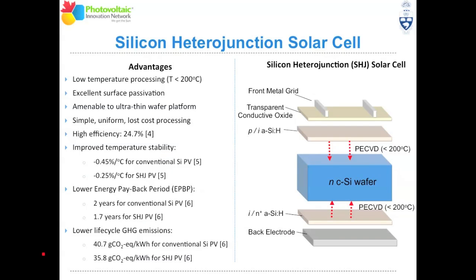So there are a number of advantages of the silicon heterojunction in comparison to the homojunction design. The two main advantages are, one, you have low temperature processing. So all the processing to fabricate the cell is done below 200 degrees Celsius. And as Kevin had described earlier in this session, with using low temperatures, you can apply this to ultra-thin crystalline silicon wafers, which has numerous advantages. Another major advantage of the silicon heterojunction solar cell is that it has excellent surface passivation.